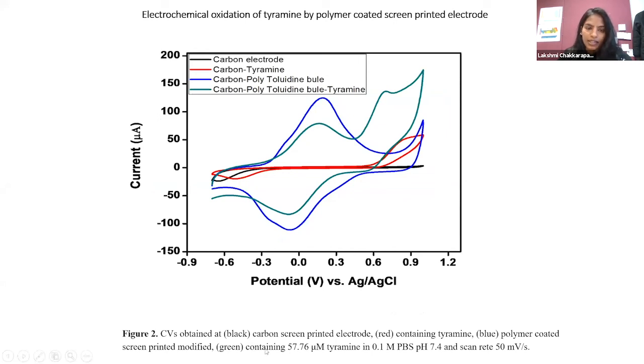Here I have represented the cyclic voltammetry response of the modified electrode and the bare electrode in the presence of tyramine 57.76 micromolar in phosphate buffer solution as electrolyte. The pH is 7.4 and the scan rate is 50 millivolt per second. We represent the peaks here. The black one is a bare carbon screen printed electrode in the presence of phosphate buffer solution. It doesn't show any peak response.